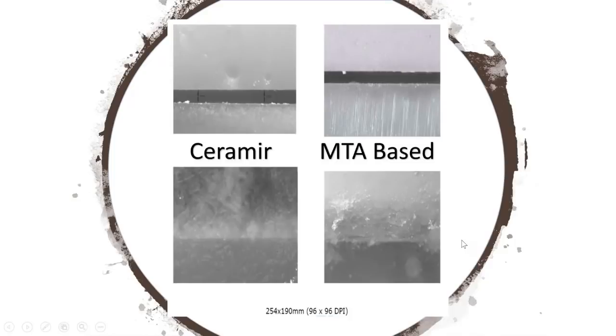And here's what's crazy. If you look here, you can actually see, let me go back, open, closed, open, closed. And why is that significant? That is so significant because there is no way everybody's putting in sealed margins. You all know it. And you all know that the cement is trying to seal that margin. And here's a study that's suggesting that potentially with calcium ion release, integrating with the saliva, you could remineralize at the margin. This is why calcium is becoming so critical in what we're doing.